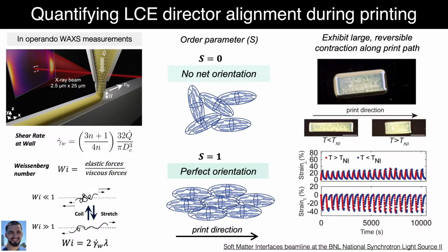But in this case, you can see that we've printed a uniaxial thick film. And in the direction where we have the director of mesogens aligned, we get substantial contraction. We think about these as artificial muscles because just like when we lift a weight with our muscles, we're contracting, right? There's a contractility. And in the opposing direction, of course, it's expanding. If you look at the strains associated with this contractile direction where we've encoded this director alignment, it's about 40% strain.